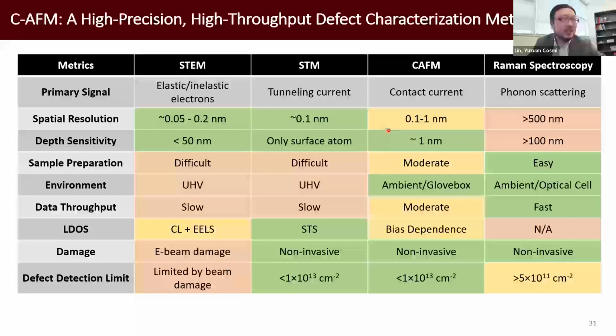For the STM, the main difficulties are the sample preparation and the limited availability of the systems. Conductive AFM has a good enough spatial resolution, 0.1 nanometer to 1 nanometer scale. For depth sensitivity, it can be sensitive to a bilayer of our sample, around 1 nanometer. Sample preparation difficulty is moderate, and we can install it in ambient or in a glove box if your material is air sensitive. Data throughput is also moderate, not as fast as Raman, but faster than the other two.